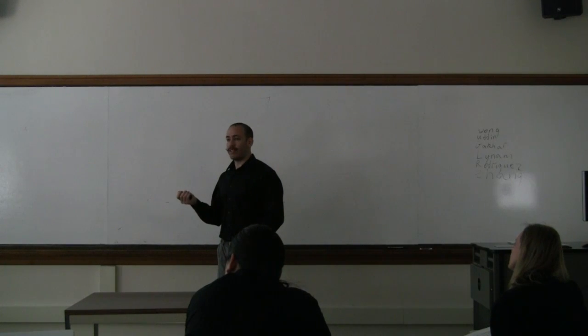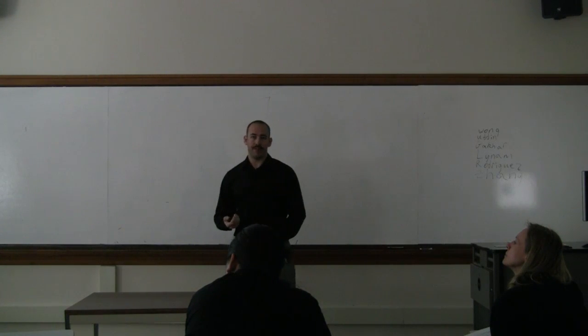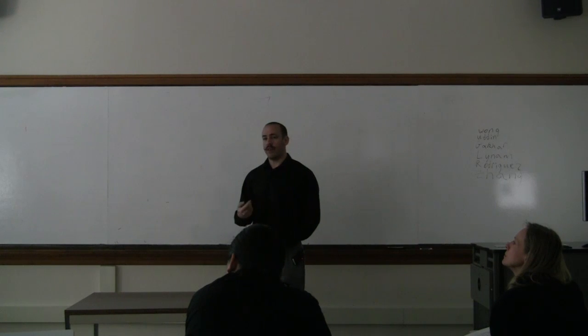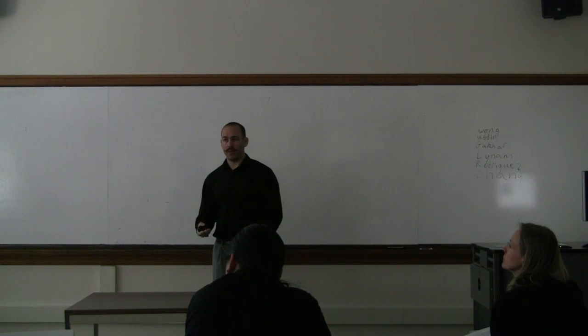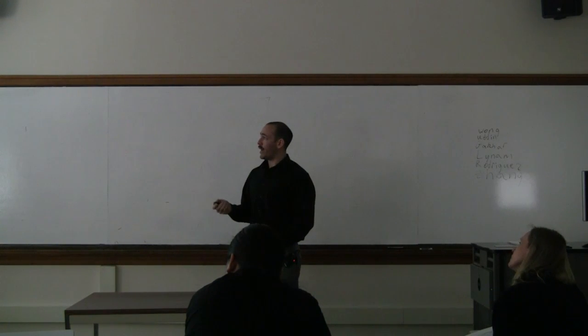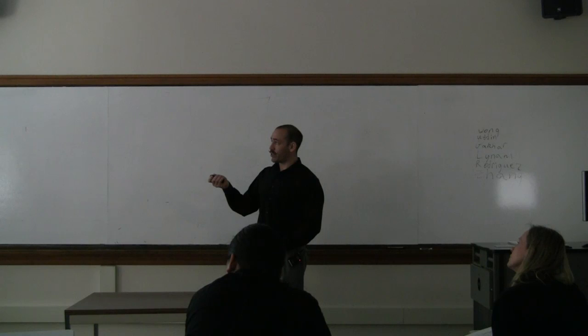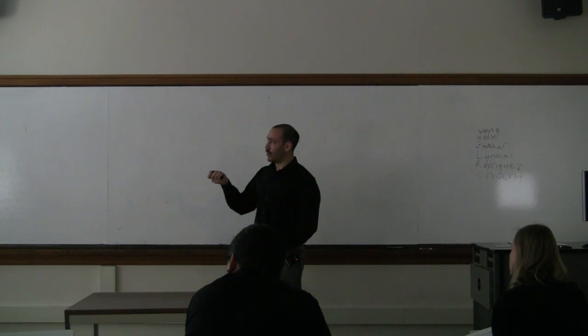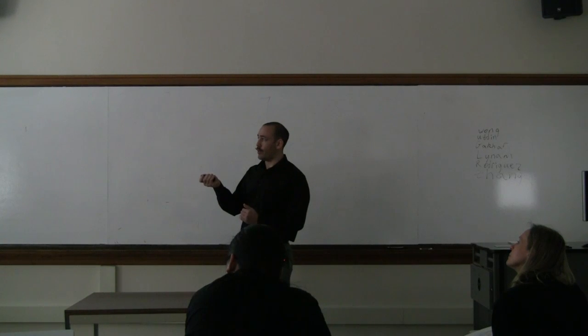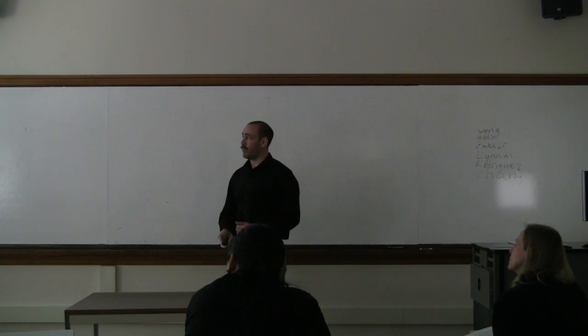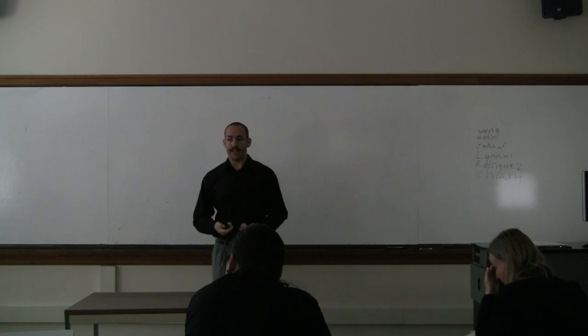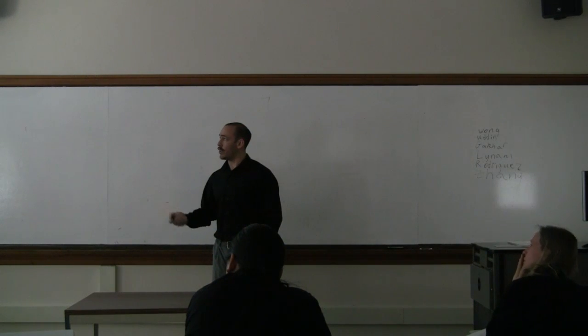Well, we take the coated sample and scratch it in a solution of 0.05 molar sodium chloride and measure the open circuit potential, and then further we will characterize the chemistry of the coating. Okay, so here we have the open circuit potential. This is where it's scratched, and similar to the previous graph that was shown in the introduction, we have it returned to the more noble potential, and this was scratched a second time, so it dropped again to the base aluminum value, and then went to the noble potential again. So this shows that it's corroding less and still protected by the molybdate-based conversion coating.